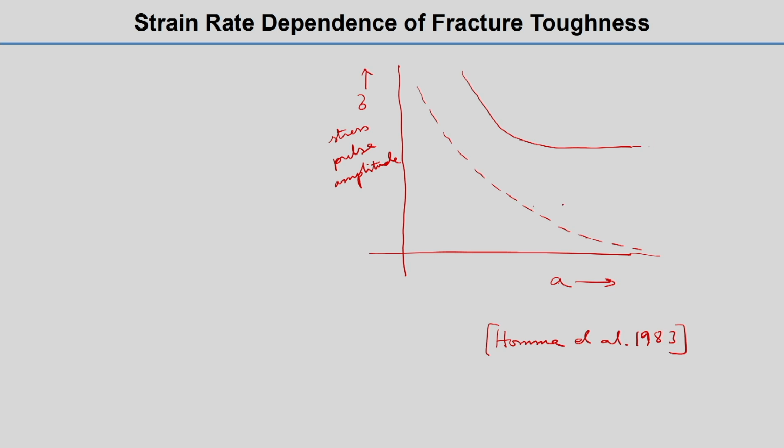The static crack, the KIC corresponding to this curve, is sigma root pi a, from linear elastic fracture mechanics. But the other experimental results, plotted after the experiments, are the dynamic case with a 40 microsecond stress pulse. So we can see that there is a significant difference between the static criterion, this one, and the dynamic one with the 40 microsecond stress pulse.